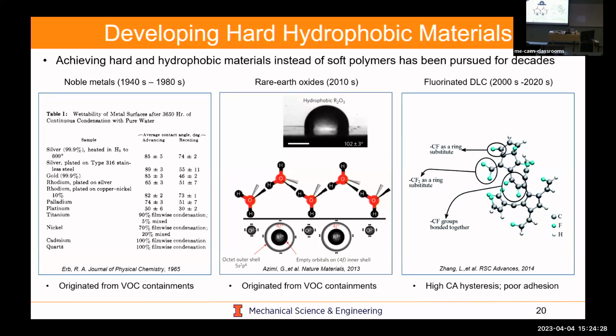People have looked at inorganic materials in the past, things like wettability of gold. Gold was actually a large topic of interest for dropwise condensation for 30 or 40 years. But it turns out that most of the non-wetting properties of gold were because of volatile organic compound contaminants that come from the air. And so this is not stable to use in a real condenser. Rare earth oxides were reported maybe 10 years ago now by a lab out of MIT, but it turns out this was also VOC, and this was kind of a scandal. I'll be honest about it. But essentially it's the same effects. What we liked was diamond-like carbon, in particular fluorinated diamond-like carbon.